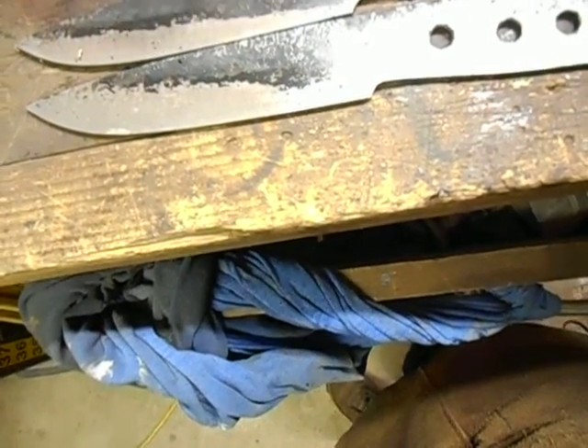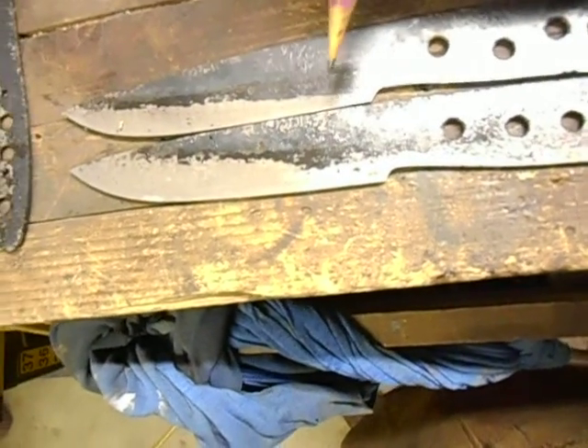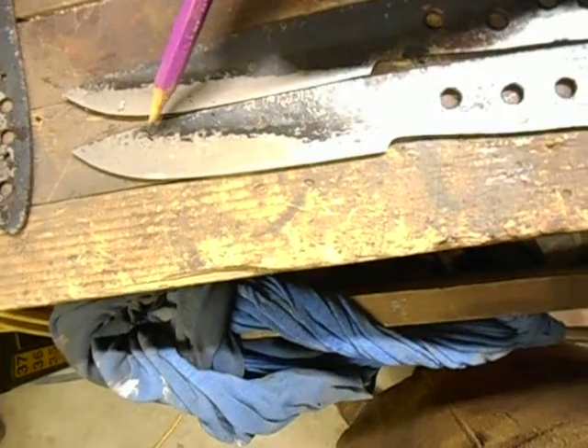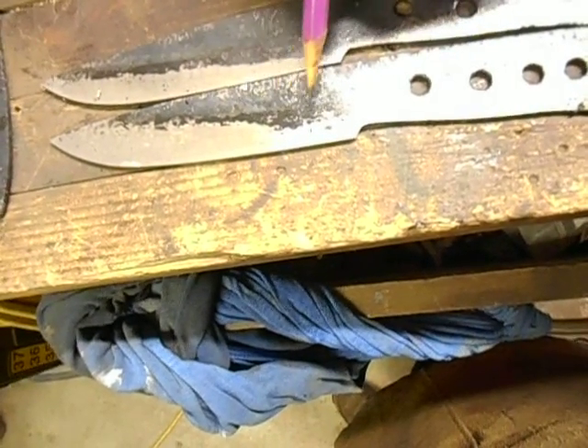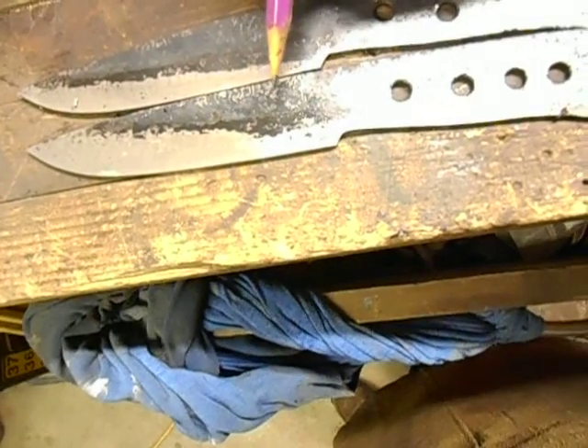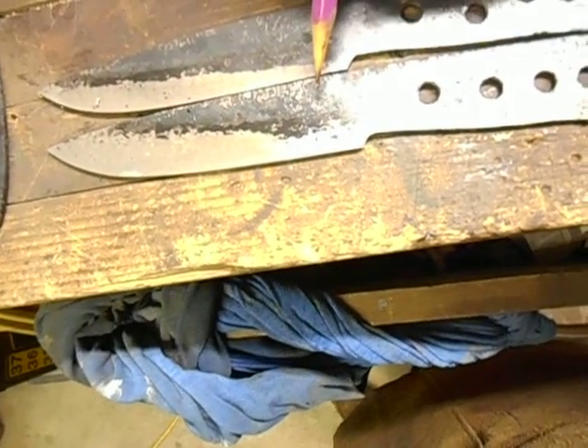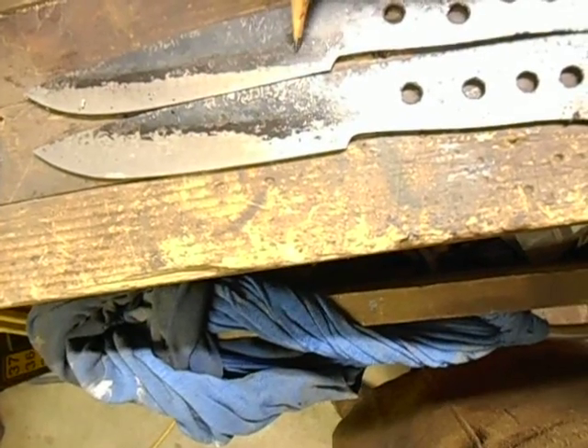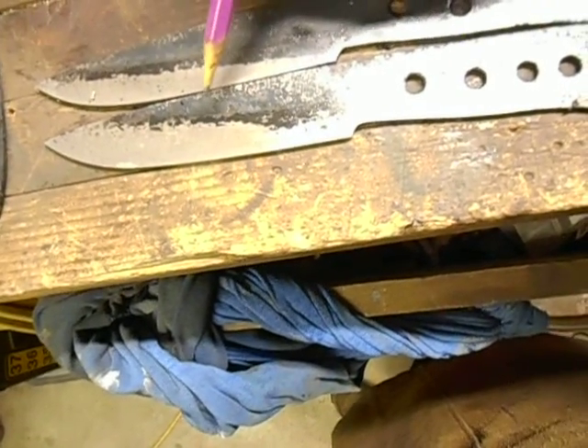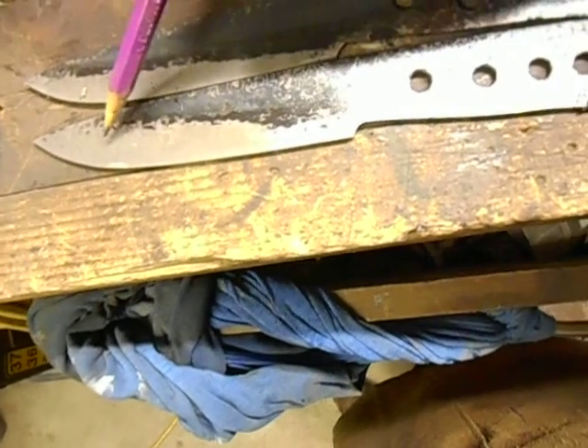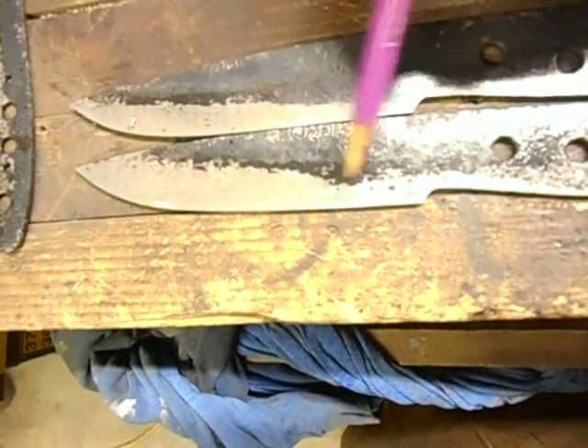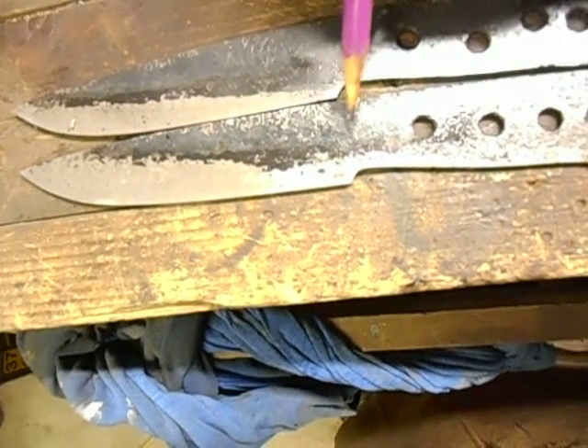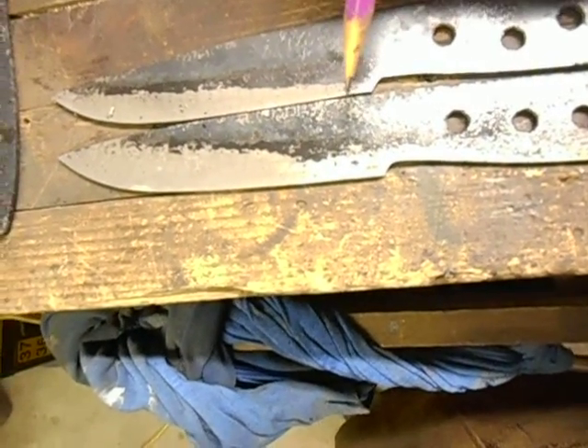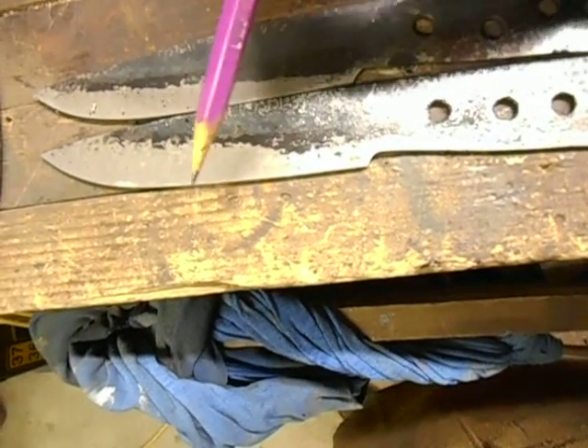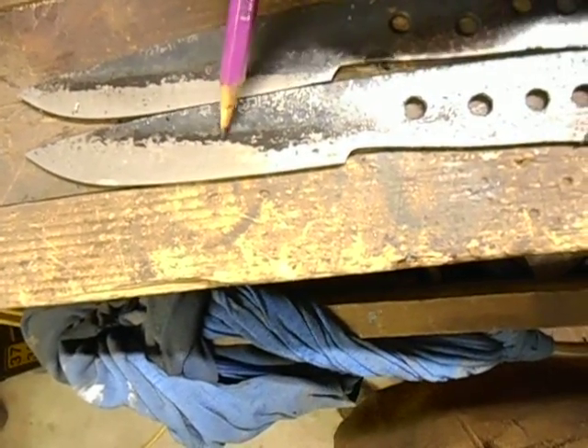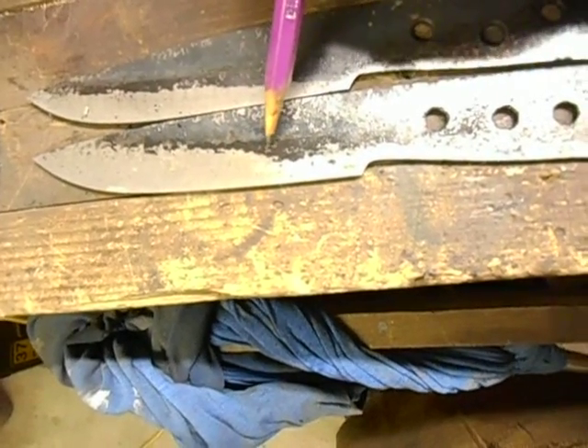And after these blades get ground, if I do hand sand them, this line right here will show up as your hardening line. A lot of people call it a temper line, which it is a tempering line if you differentially temper the blade. I do differentially harden the blade, whereas just this portion of the blade gets put into the oil and gets hardened. The rest of this steel, while it will get a little bit of air hardening going on, isn't really hardened to the same effect that the edge is, and so it's a differential hardening heat treatment.